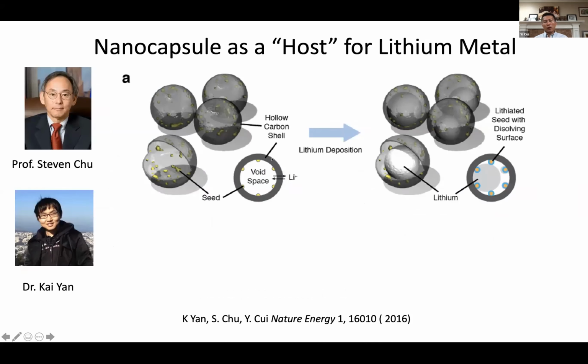In this case, we construct a carbon host. We also found that for the carbon, there's a nucleation barrier, but for gold nanoparticle seeds you put in, there's no nucleation barrier. You can have lithium diffusion, electrons coming in, and lithium deposition happen inside the hollow carbon instead of outside. Now spatially, you have control of where lithium will go. Then this carbon would help to form an interfacial layer to react with the electrolyte. You possibly can build a stable SEI. So that's the underlying concept.